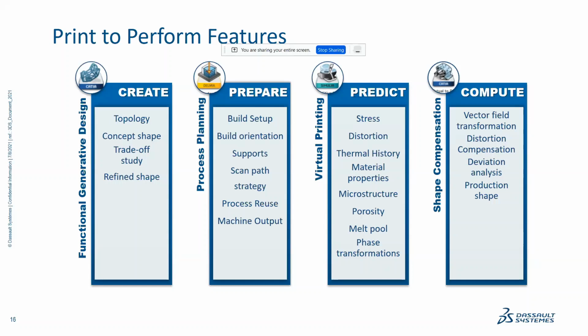The virtual printing, where we are looking at the thermal history of the part being printed, in the process of solidification of the powder into the part, the different material properties along with its microstructure and porosity that occur at the melt pool phase transformations, which eventually result in the distortions due to strains or residual stresses that are developed during the process of phase transformation and melt solidification. So we have developed the necessary tools, which I'll be talking about over the course of this session, and share with you the different technologies that we offer for enhancing the value of the design simulation.